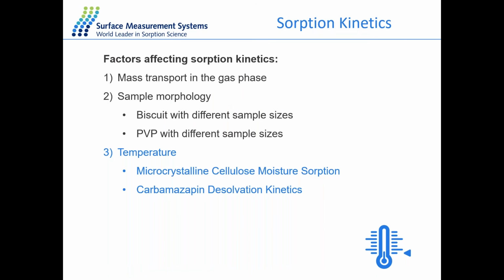And the last factor that will improve the sorption kinetics is the temperature of the experiment. Generally, a higher temperature will give more energy input for the moisture diffusion. Therefore, it will result in faster kinetics for the moisture sorption. And here we have two different examples, with microcrystalline cellulose material and with carbamazepine for the desolvation kinetics.